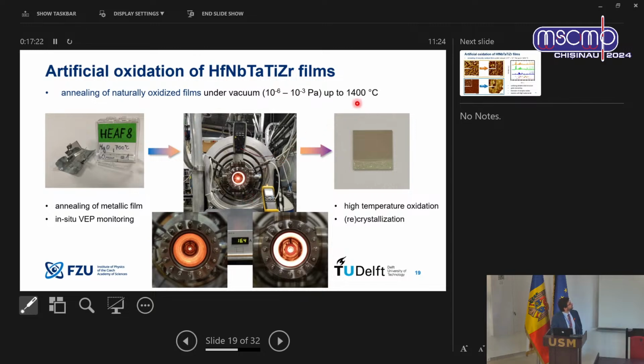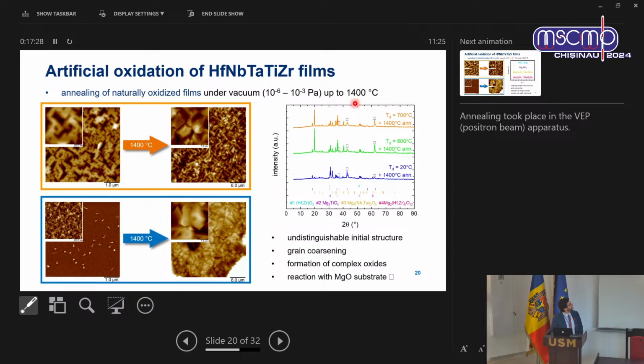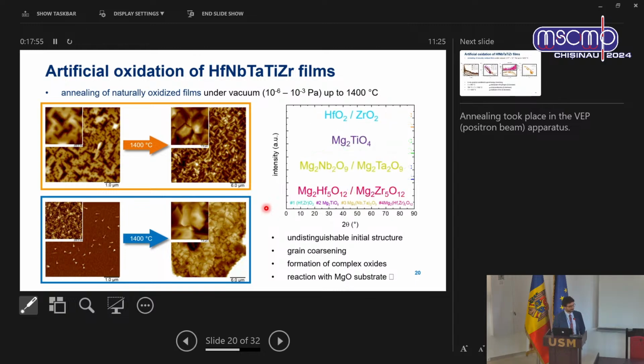Well, the morphology looked promising. We really increased the grain size massively. Also, the final state was more or less the same regardless of the initial state, if it was nanocrystalline or amorphous. But the phase analysis showed that we didn't actually obtain a single phase at all, but instead we got a mixture of oxides. And really, really complex oxides because there was a reaction at the surface with the residual oxygen in the vacuum, also a reaction with the oxygen from the magnesium oxide substrate.